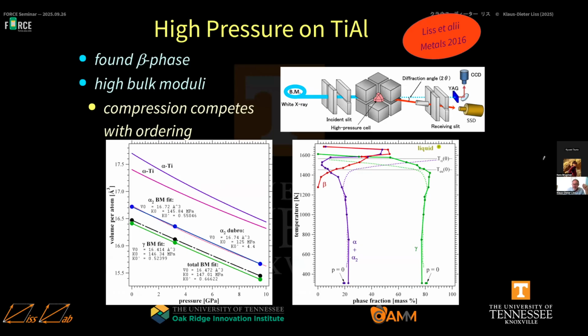Okay. What I want to show here is, as a function of temperature now on the vertical, the phase fraction of different phases. So at ambient pressure, P equals 0, we have this dotted data. And you see the dotted data go here and here for the alpha and alpha 2 phase, which is a hexagonal phase. And the gamma phase is the ordered FCC-based phase. You only have the two phases. So the one goes up and the gamma goes down as a function of temperature. And eventually you have an alpha transus. This is when the gamma phase disappears.